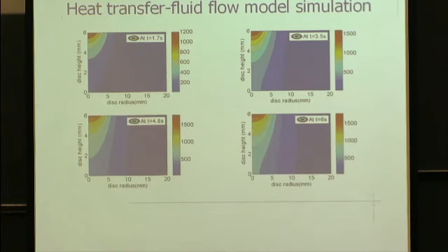So if you know all the parameters quite well, you can do a simulation without any problem, and you get some result. So here, this cartoon depicts basically the temperature field at different times. So at this one, 1.7, we have applied the heat load on the top surface, and as the thermal conductivity is equal in all directions, you have a sort of quite normal quadratic propagation or something else, I don't know. So it is after different time steps, and we can see that around 3.5 seconds we start to melt on the top of the surface.